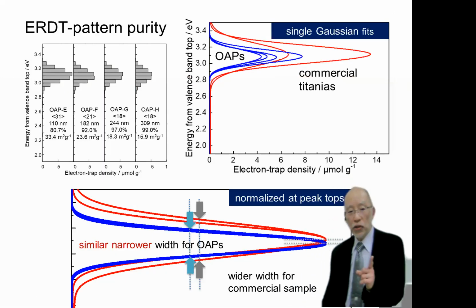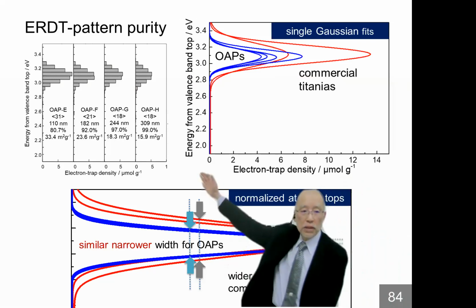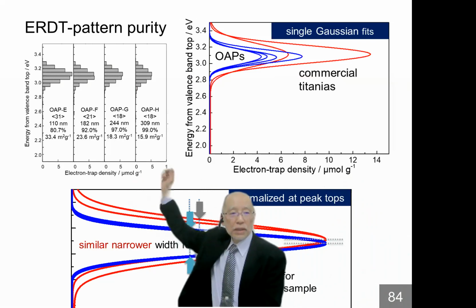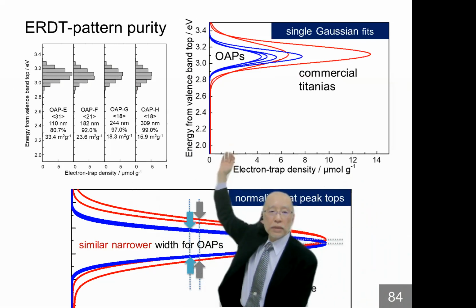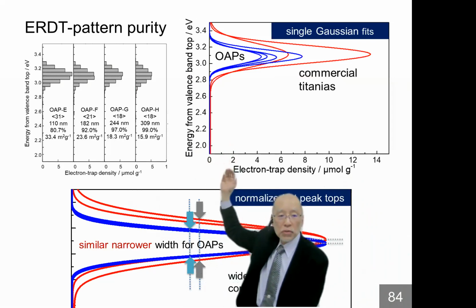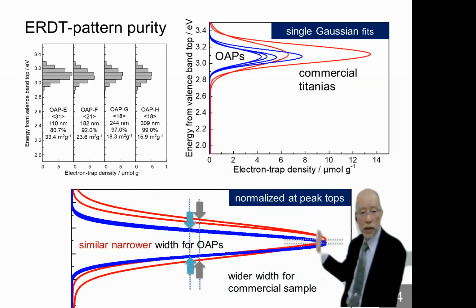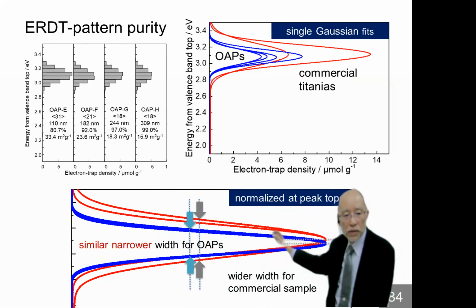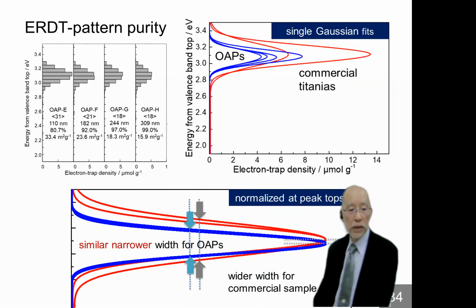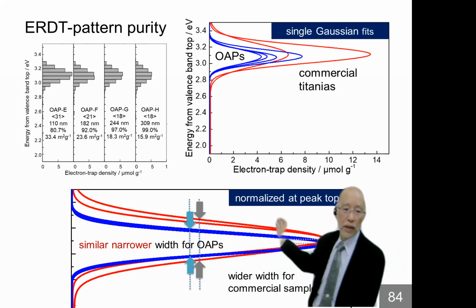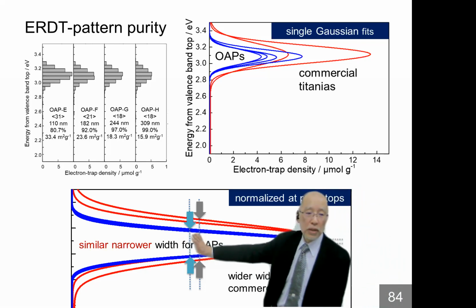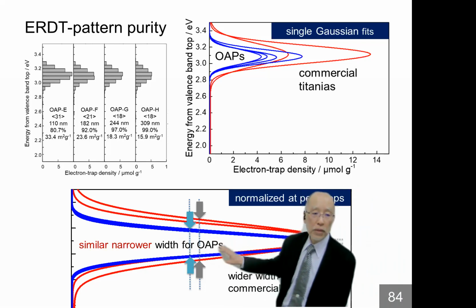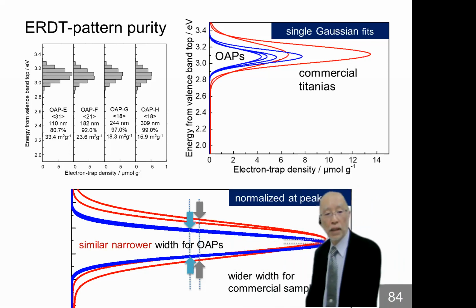And then by measuring the ERDT pattern, this is the result. Depending on the size, the total density is different, but a single Gaussian fit gives almost the same shape of ERDT pattern for octahedral anatase particles. And by normalization at the peak position, these blue lines for the OAP samples, octahedral anatase samples, are almost the same. And the half height width is much narrower compared with commercial titanium oxide patterns.